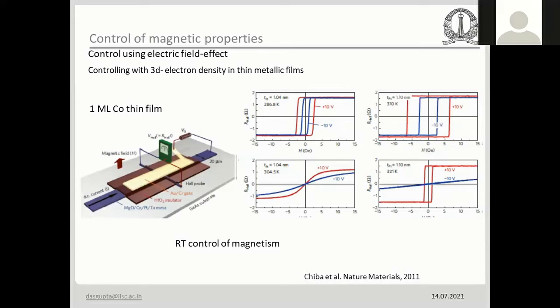So for 1 monolayer of cobalt, now the success is a bit more. You can see that they could control the coercivity and also they could control the magnetization. You can see that in this fourth plot here on the right hand side, for plus 10 volt they have a magnetic material, and for minus 10 volt it's nearly paramagnetic, or you can really call it on and off switching of magnetism. But that's possible only for very thin film if it is a metallic magnet.